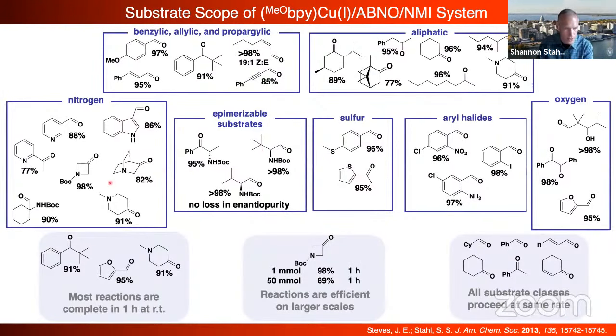Finally, just with respect to synthesis, maybe if there is a point about the synthesis, it's the functional group compatibility. Note the presence of tertiary amines. In fact, Iwabuchi has done some similar chemistry with primary amines and secondary amines. You can see free anilines in this system. You can see unprotected indoles. These are very electron-rich groups that many oxidants would annihilate.